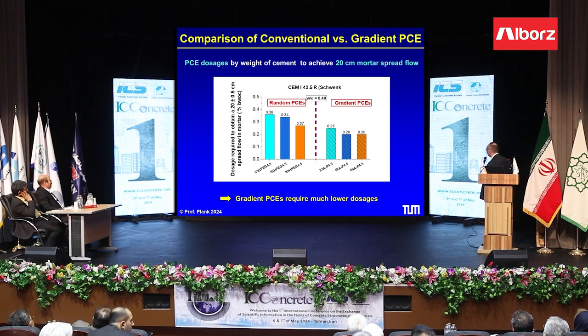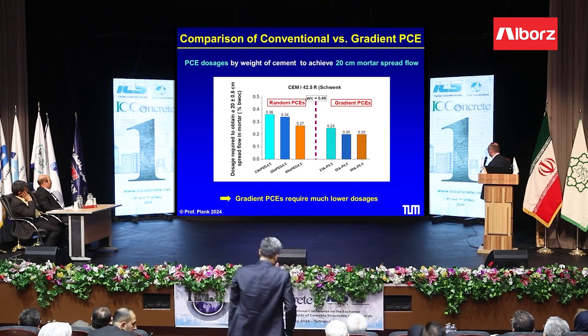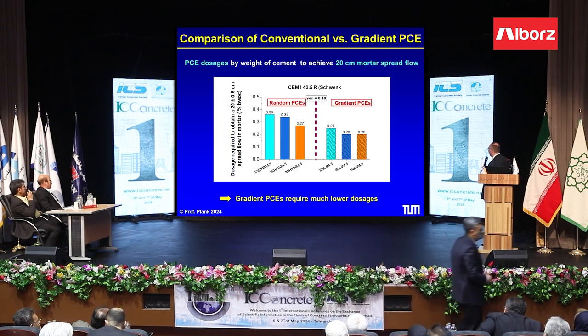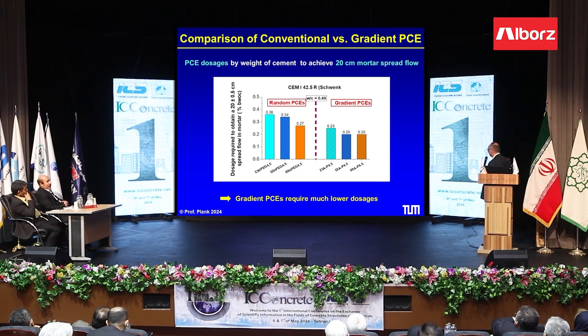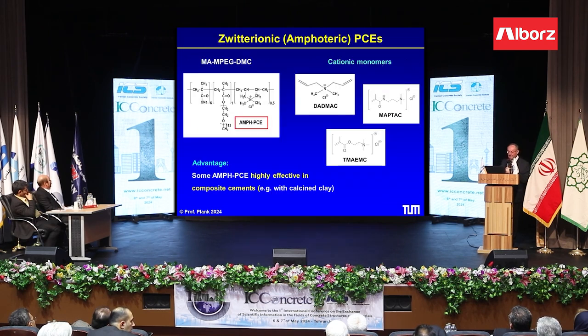Here I show a comparison of different HPEG PCEs with different side chain length. The molar ratio is constant. They are made in the conventional method. These are the dosages which are needed to reach 20 centimeter spread flow. If we make them as a gradient polymer, you see the dosages are about 1/3 lower to get the same spread flow. So these optimized molecular structures actually can make them a lot more cost effective.